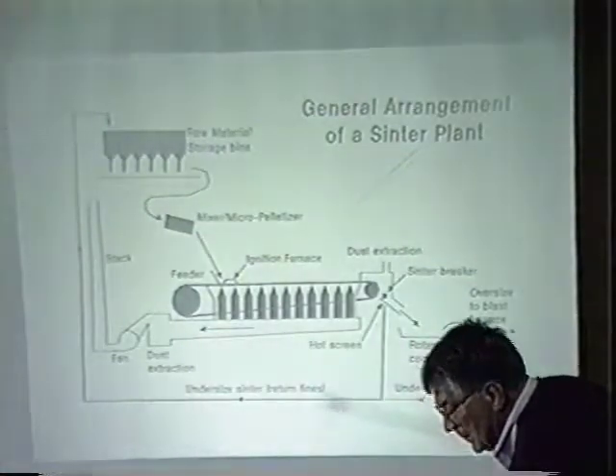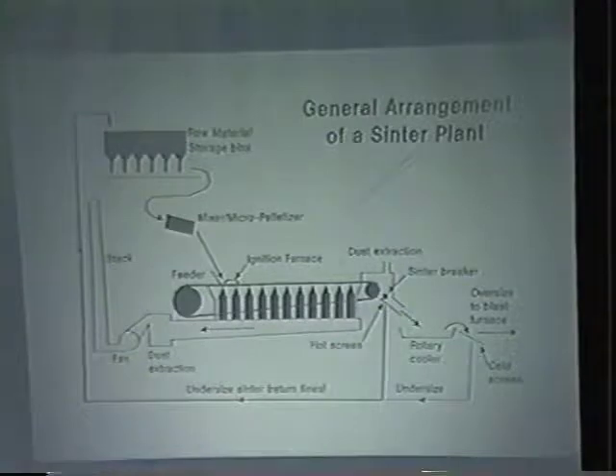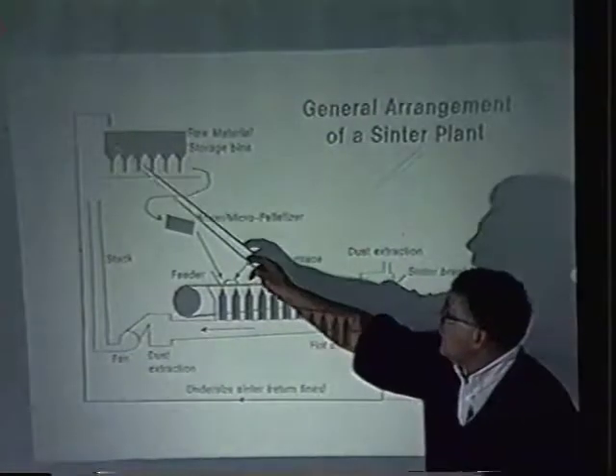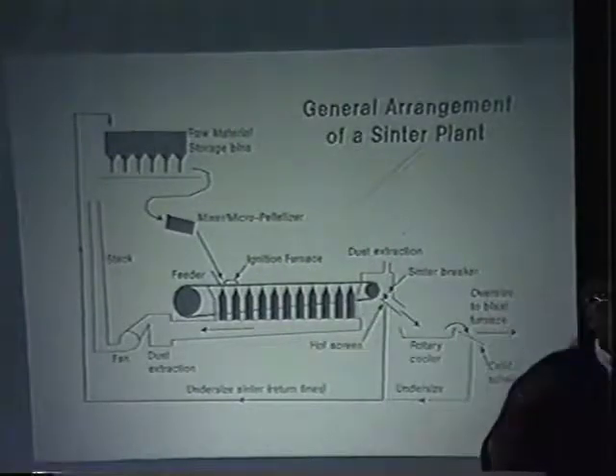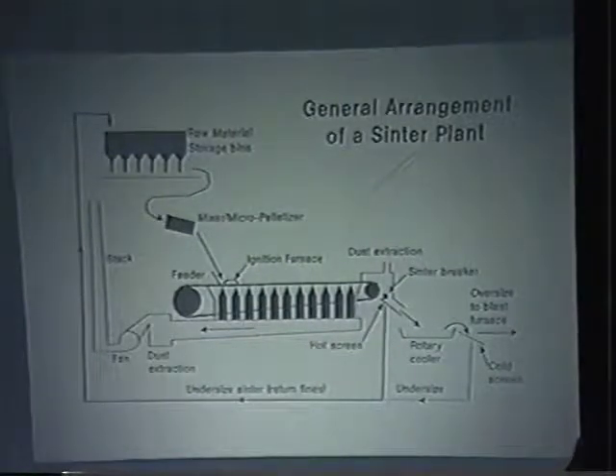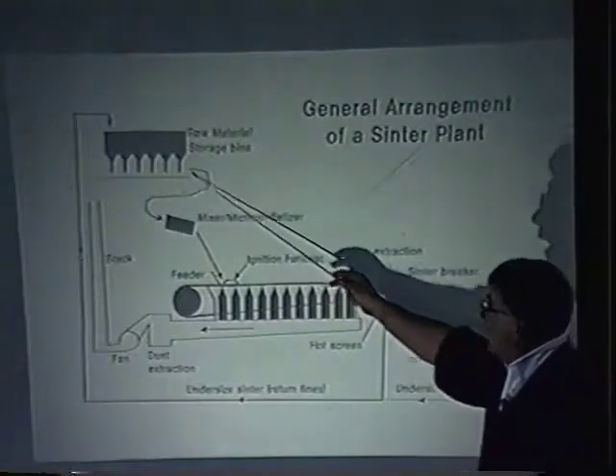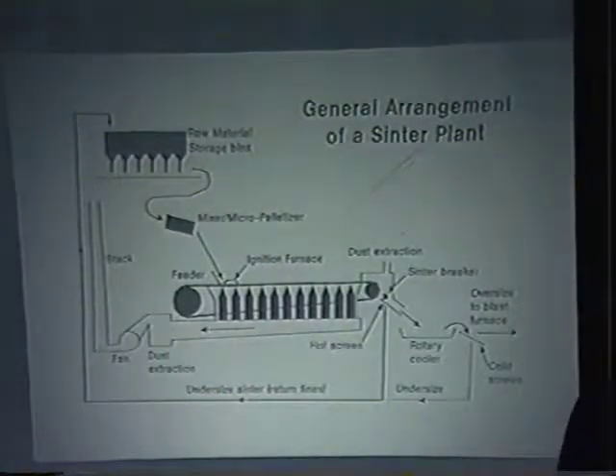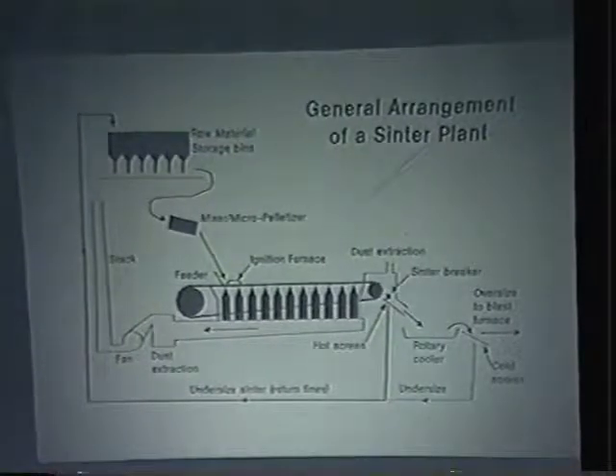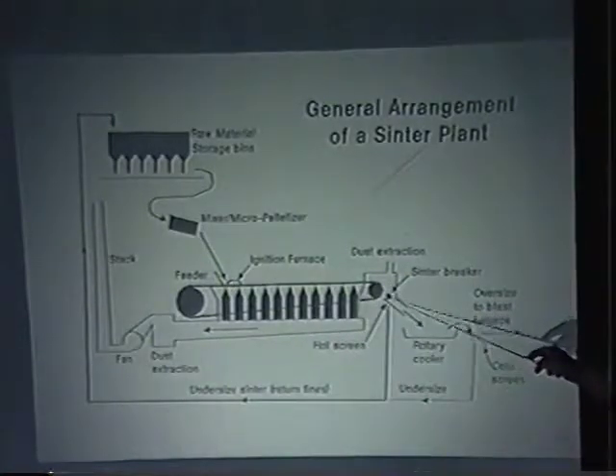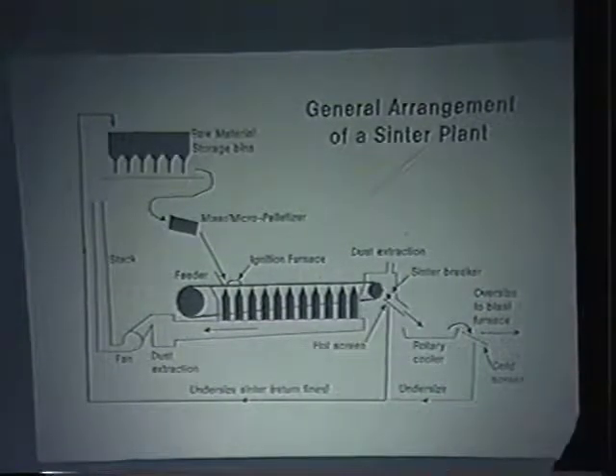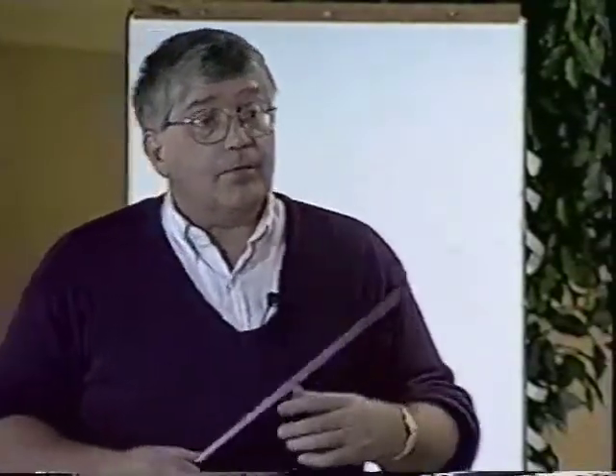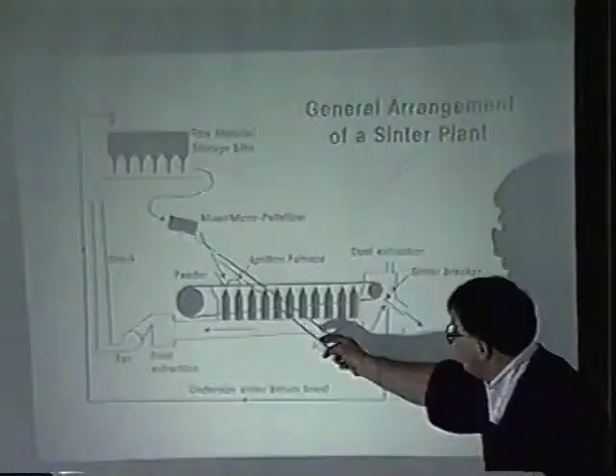Now the sinter plant is kind of a neat operation. They take all the storage material from the bins, the raw materials, and we have some other things. We have iron ore fines that we use for trim. We have coke breeze we use for trim, and coke breeze is a byproduct of the coke oven. They take this material and they put it through a micro-pelletizer, which is a nice fancy name, but all it does is it takes the powder material and makes it into little tiny balls, so that when we put it on the sinter machine, which is a long steel conveyor belt, it has voids, and we need the voids for permeability, because what happens, the material feeds on this side.